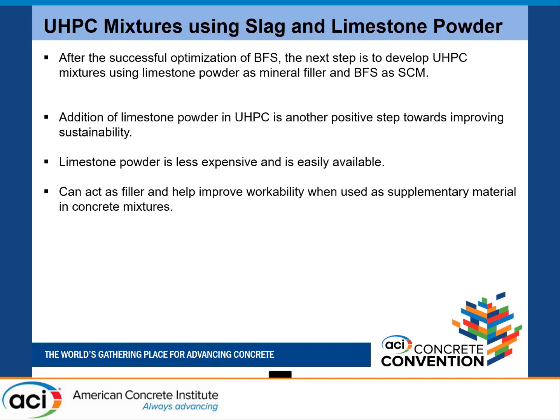Why should we waste supplementary cementitious materials like cement, slag, or fly ash just to use them as fillers? So we can take out that portion and use a filler like limestone powder, which is cheap. Therefore, we are now trying to replace cement with limestone.